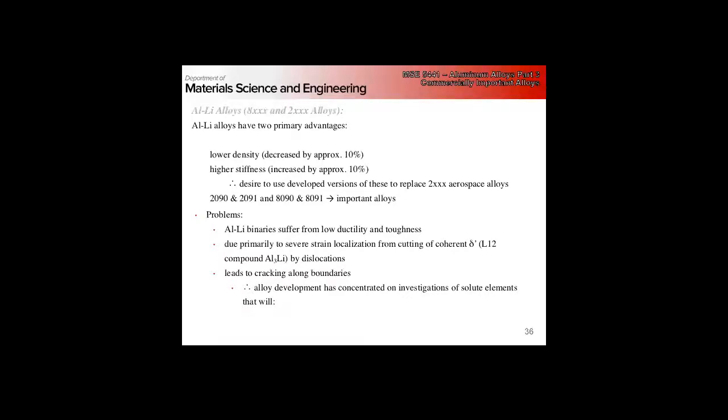These same problems - I sound like a broken record. High strength, low ductility. Looking back on the notes, the general trend is that the more that we are reliant on particle strengthening or aging precipitation hardening to give us our strength, the worse our toughness and our fatigue resistance is going to be. You see this trend play out again and again and again.